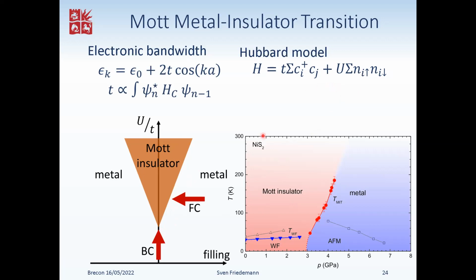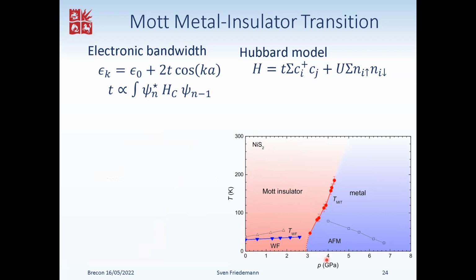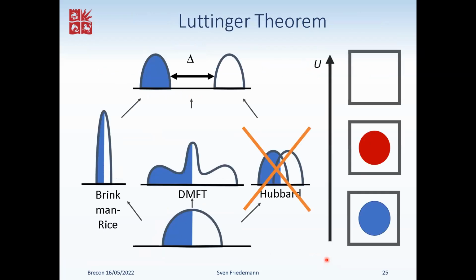So we can study this with high pressure, and in fact we've done some measurements on nickel disulfide, which is a Mott insulator at ambient pressure. As you cool down, you get some magnetic transitions, and you can turn it into a metal above about 3 GPa, which does necessitate the use of diamond or other gemstone anvil cells. We've done exactly that. So we're asking ourselves, essentially, can we probe Luttinger's theorem here?